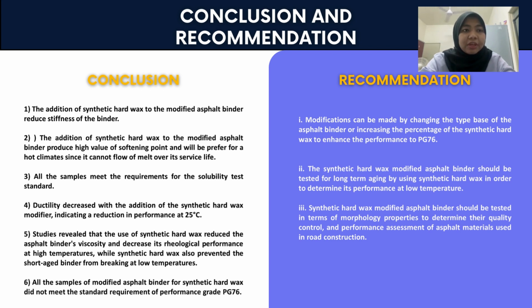For the conclusion, first, the addition of synthetic hard wax to the modified asphalt binder reduces the stiffness of the binder. Second, the addition of synthetic hard wax produces a high value of softening point and will be preferred for hot climates since it cannot flow or melt over its service life. Third, all the samples meet the requirement for the solubility test standard.